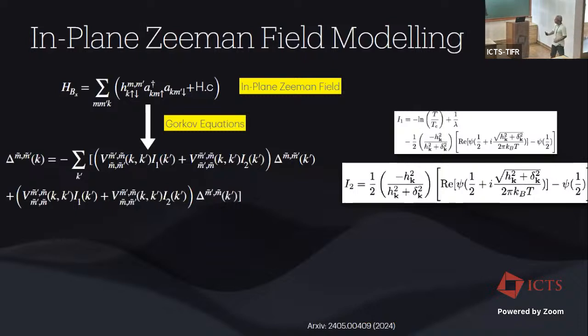So then we looked at the magnetic field dependence. I won't go into the details of it, but the point I want to make is that even if you look at the in-plane magnetic field component, or even restrict yourself to a homogeneous solution, not looking at the FFLO or other phases, you cannot separate out, in principle, the magnetic field dependence from the gap matrix itself. If you want to work with the Eilenberger type of formalism, you have to approximately separate out singlet and triplet. But what we have tried to do here is solve the full gap matrix with the magnetic field without using that approximation.